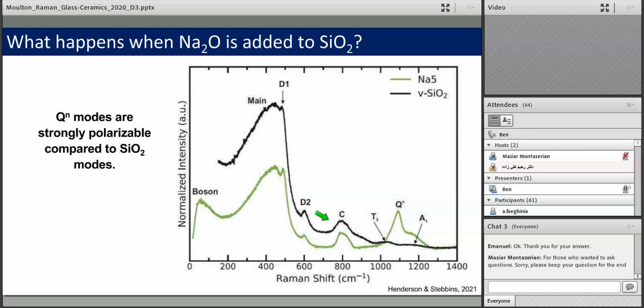So that's silica, but what happens when we add some modifier oxide into the mix? When you add just 5% sodium, the spectra stay roughly the same. These are offset, but you can see that the shape of the envelope is pretty much the same. We see the D1, the D2 bands here. We see this cage rattling here. What you get is a slight difference in intensity around 900.